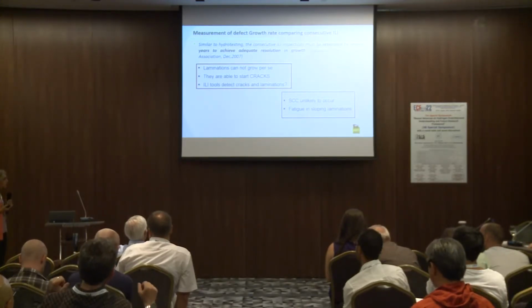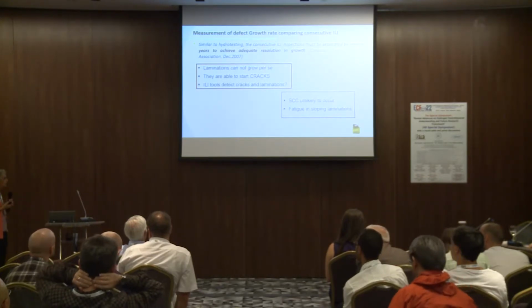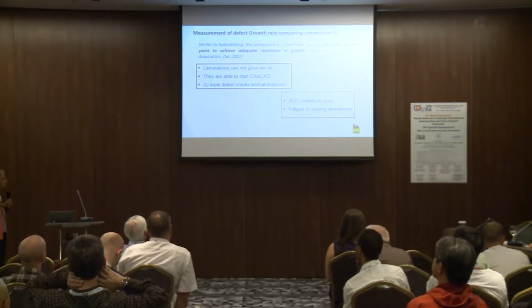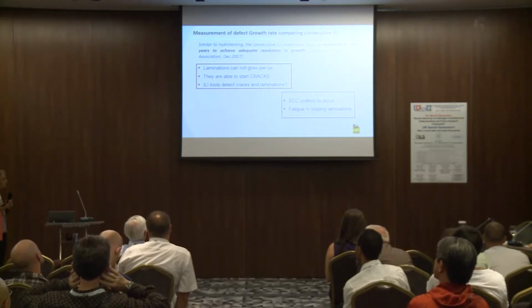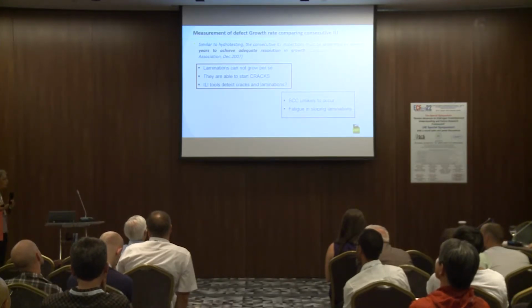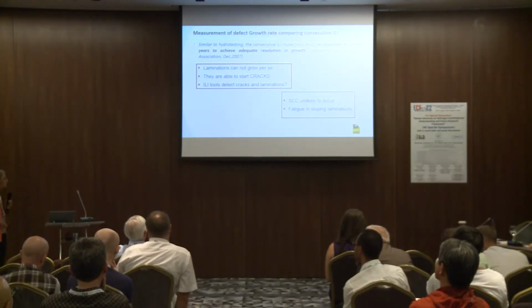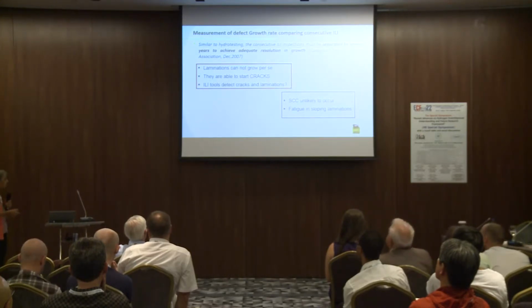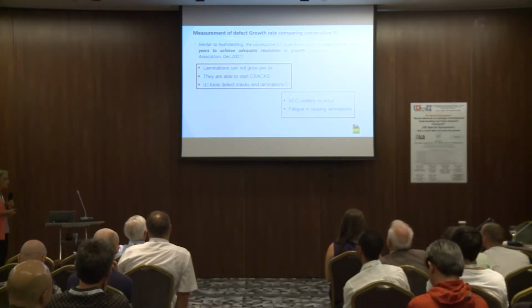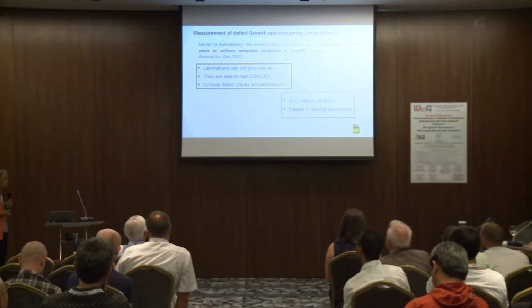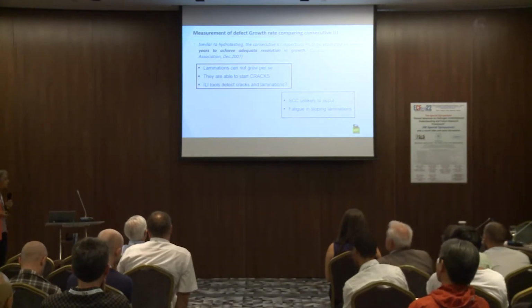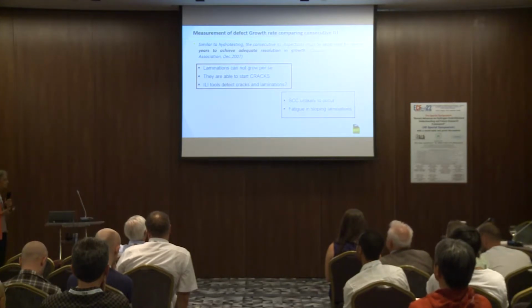So H2S is a poison for the recombination of hydrogen. But if the water doesn't dissociate, probably we don't have atomic hydrogen. And so the effect of H2S can be much lower than what we think. While the problem of fatigue and sloping lamination is probably much more important, but there is no corrosion here because the water or the fluid doesn't reach the center of my pipeline. So this is our speculation. I don't know if they are all correct.